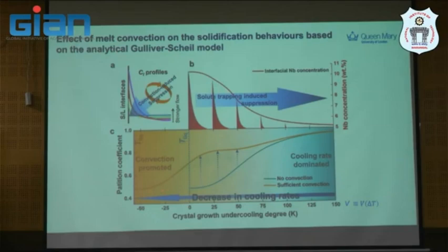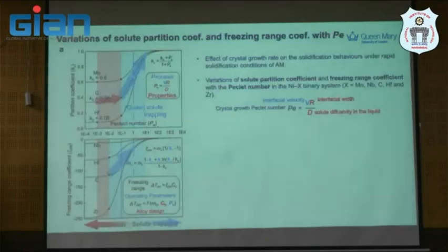And that's actually the promotion of this convection giving rise to the increase in the undercooling temperature of the crystal growth. So if there's sufficient convection, it will increase the undercooling, and the partition coefficient, which is K, will be increasing. So this gap here will lead to a difference in the partition coefficient during processing. And that is what it is here, the variation of partition coefficient, this is partition coefficient K, and then this is the Peclet number, which is linked to the crystal growth of the process.